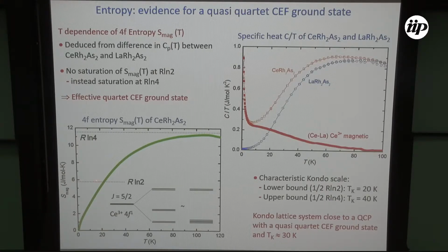And what is remarkable here is that there is no saturation, no evidence for saturation at R ln 2. There is a saturation at R ln 4. And here it's going straight through. This indicates that the first excited state is not very far above the ground state and is within the Kondo scale of the ground state. So they are both mixed, and then we have effectively something like a quasi-quartet crystal electric field ground state.